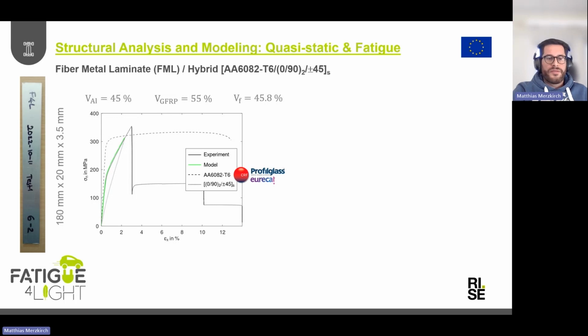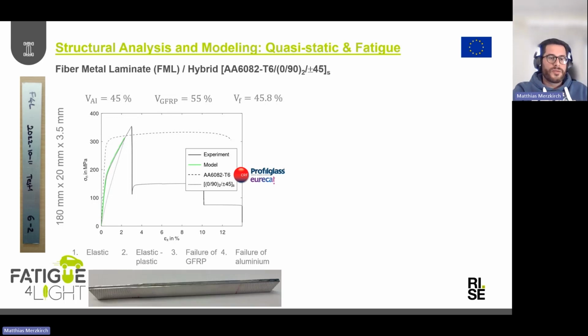We have different types of failure or deformation here. First, we have pure elastic deformation. The second part, the second slope here, is elastic-plastic. Then we have the failure of the glass fiber inside the specimen. And then one aluminum layer is failing, and then the second one. This is the elastic-plastic deformation of the aluminum layer. Using the rule of mixtures, again the model in green, we can at least predict the first two areas there.